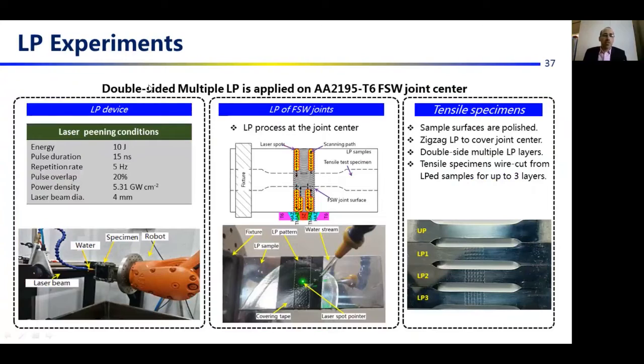For laser peening experiments, double-sided multiple laser peening is applied on both sides of the joints up to 3 layers at the joint center where lower mechanical properties were observed. The laser is applied with the power of 10 joules, which asserts the laser spot with the 4 millimeter diameter on the surface, and laser peening is applied with a zigzag pattern to cover all over the joint central areas. And subsequently, tensile specimens are cut from the laser peened samples.